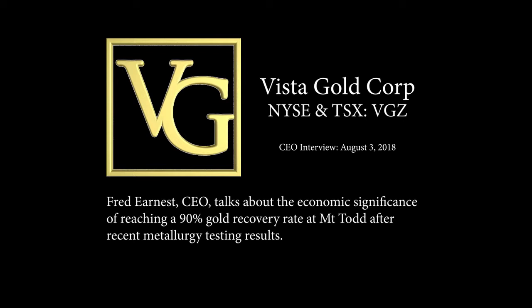And so we completed two sets of tests. These tests indicate that at grind sizes of 38 and 25 microns, or in other words, about two-thirds and a little under half the size that we had targeted in the last update of the PFS, that we will achieve recoveries at or in excess of 90%. And this is a very significant step forward for the project, being able to reach this point.